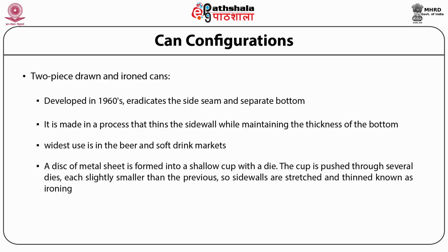Starting with a plate thickness of 292 micrometers, the side walls are reduced to 97 micrometers, while the bottom thickness remains the same. This process of pushing the cup through progressively smaller dies is termed ironing of the side wall. As the walls are ironed, the bottom is domed to provide strength and stability. The maximum ratio of height to diameter allowed is 2:1.